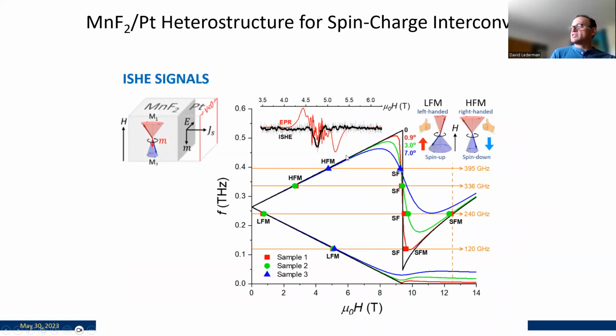So this is the data right here. The red here is the resonance frequency of the antiferromagnet, the manganese fluoride. The black signal here is the inverse spin Hall effect voltage, right? And you can see that it coincides really well, which is what you want. The other thing that's nice that was done at the lab is that you could do right-handed and left-handed polarized microwaves, and you could make sure that you're selecting the correct mode.